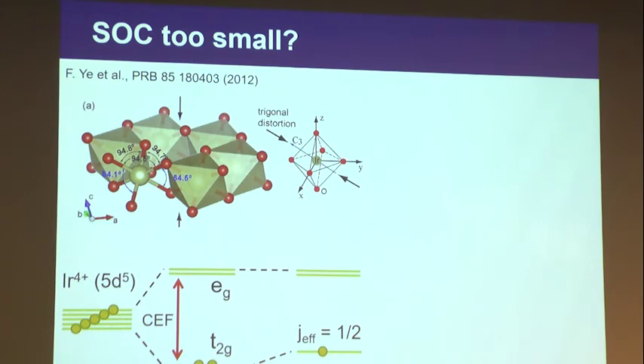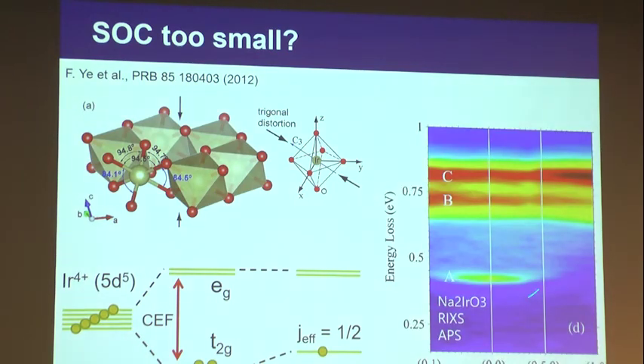And that gives you additional splitting in the energy levels that splits these two levels. And you can study that using RIXS. In the work done here at the APS, we were able to measure the splitting between these two energy levels and show that it is much smaller than the whole energy scale. But that also gave us an idea that the way to make ruthenium, or other materials with a smaller spin-orbit coupling, work is to find a material which has an ideal cubic or octahedral geometry.